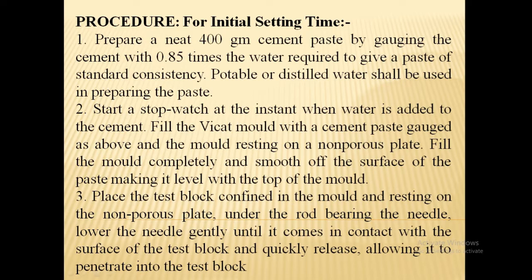Lower the needle gently until it comes in contact with the surface of the test block and quickly release, allowing it to penetrate into the test block. Repeat this procedure until the needle, when brought in contact with the test block and released, fails to pierce the block beyond 5 ± 0.5 mm measured from the bottom of the mould — that shall be the initial setting time.